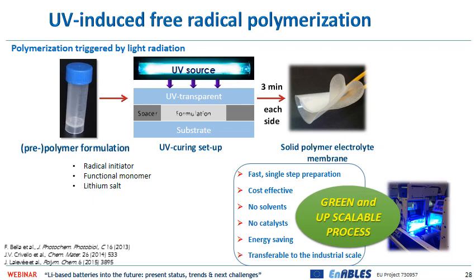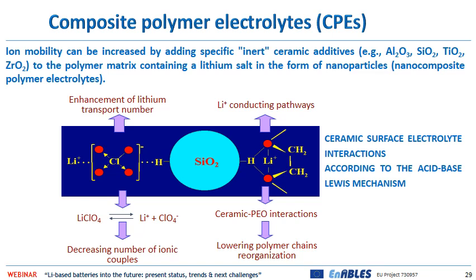In order to reduce the glass transition temperature, for example of PEO, a really simple and fast preparation procedure is UV curing, which we use in our labs and is also possible to transfer to the industrial scale. Composite electrolytes are solid polymer electrolytes with submicron or nano-sized inorganic particles dispersed in the polymer matrix. Adding inorganic particles induces a favorable interaction between the ceramic surface states and the anions of both the lithium salt and, for example, PEO segments, thereby promoting lithium-ion transport and inhibiting polymer crystal-like formation. This results in enhanced ionic conductivity, promoting interfacial stability at the lithium metallic electrolyte interface, suppressing the growth of dendrites, improving mechanical properties, and increasing lithium transference number.